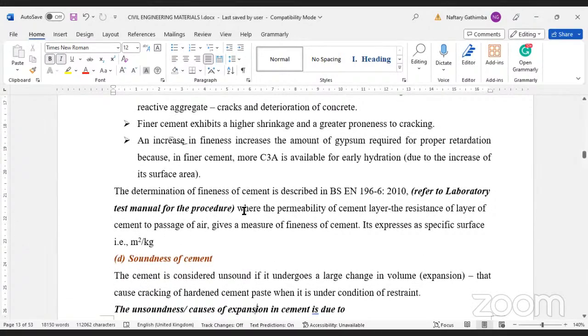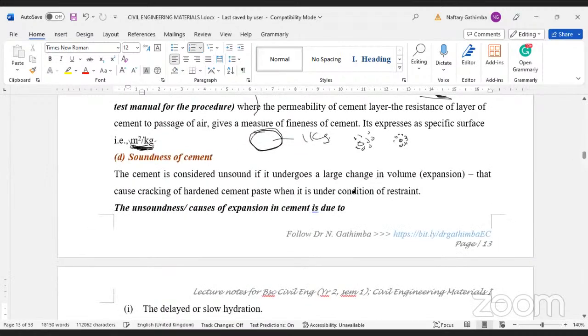Because I wanted to say that there is a test in the lab that maybe you'll conduct. Currently, we do not have our equipment working, which tests the fineness of cement. So the fineness of cement is given in terms of the surface area. Like if we have 1 kilogram of cement, if you break it down to smaller particles, the surface area is increasing. I hope people can understand that. If you measure the surface area around these particles as you continue breaking them down, it's more than when you have one big lump. So it tells you that the higher this value, surface area per kg, the finer the cement. We use what we call the Blaine's apparatus in doing this test. I can't assure you that you have it in the lab.